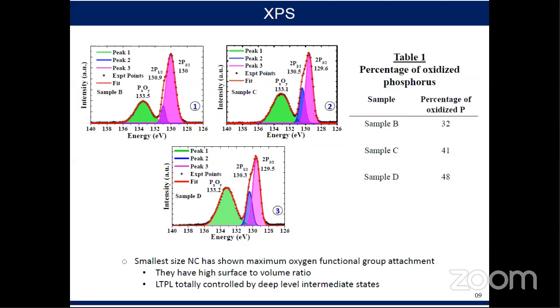So as we can see in comparison to sample B and C, sample D has a stronger oxygenous band. So from table 1, we have extracted out that oxygenous phosphorus contribution, and we can see that sample D has almost 50% of the phosphorus oxidized. So that is why it is showing this negative thermal quenching behavior. As I said, it has the largest surface to volume ratio, so it has the largest density of these functional groups.